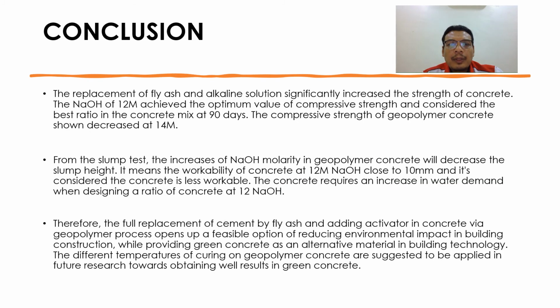Now I'm going to explain the conclusion of this research. First, the replacement of fly ash and alkaline solution significantly increased the strength of the concrete. The sodium hydroxide of 12 molarity achieved the optimum value of compressive strength and is considered the best ratio in the concrete mix at 90 days. The compressive strength of geopolymer concrete shown decreased at 14 molarities.